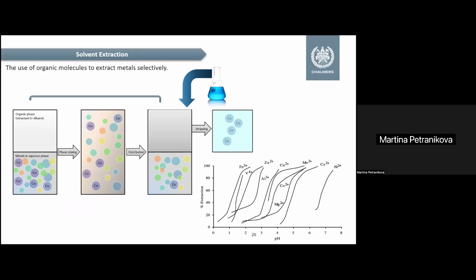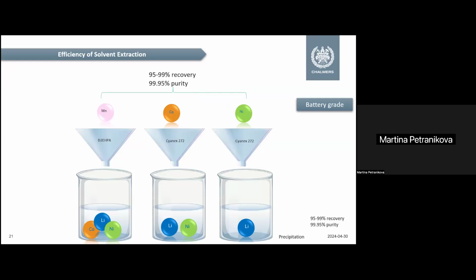So sometimes solvent extraction is seen as a very chemical-consuming process, but it's actually not, because these molecules can be used, and some companies are using them for 10 to 30 years. They can be reused again and again. For the separation of these elements, usually we use different organic molecules. For manganese, it's very often the commercial D2EHPA, and for cobalt, it can be Cyanex 272.